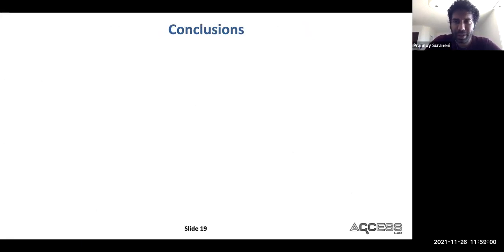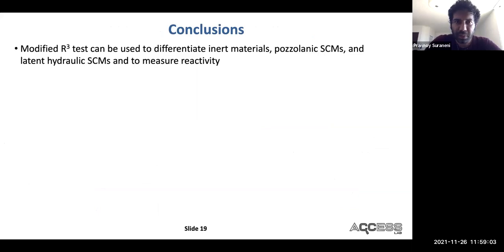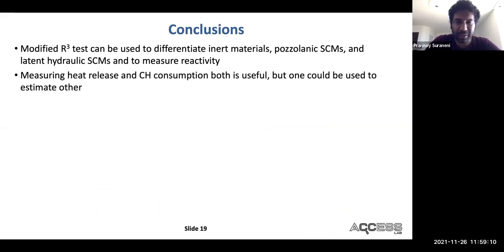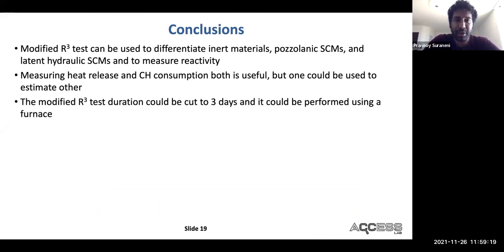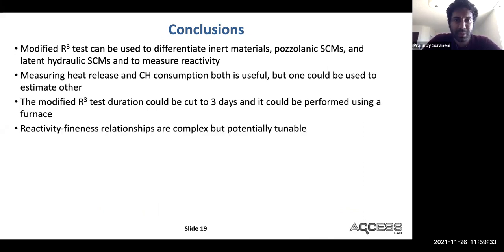So with that, I'd like to conclude my talk. So essentially, the modified R3 test is great. It can be used to differentiate inert, pozzolanic, and latent hydraulic materials. I would suggest that you measure both heat release and calcium hydroxide consumption. But if you're smart about it, one can be used to estimate the other. You can actually cut the test duration to 3 days. You can get almost the same amount of information from a furnace. And a 3-day test could be really useful for standards and specifications.